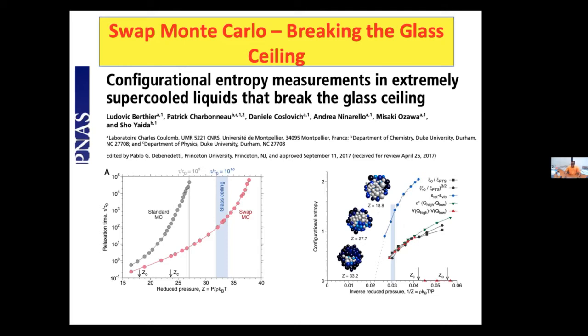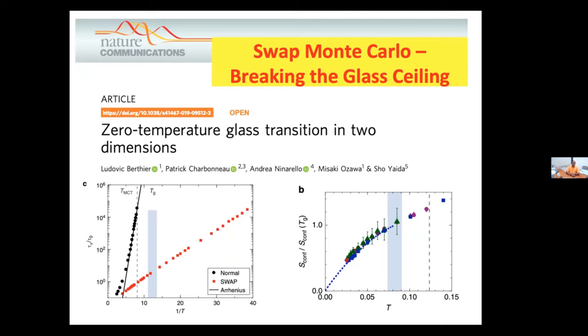Based on this success, they went on to look at the glass transition in two-dimensional systems. It is important to highlight that, due to the Mermin-Wagner theorem, it is known that one cannot have long-range crystalline order in two-dimensional systems. So the question was, can one have a glass transition in 2D at a finite temperature? Again, due to swap moves, if I quote the number given in this paper, the speed up compared to conventional simulation is 10 to the 47, which is an astronomically large number. Even if you don't believe those numbers, the speed up is impressive, and one can reach extremely large relaxation times.